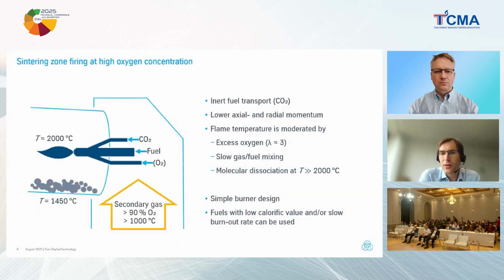Let's have a look a bit more into the details. First, the question: how is it possible to operate the sintering zone with this more or less pure oxygen while maintaining the required process parameters? And the clue in this approach is that due to the low gas volume of the oxygen compared to the nowadays